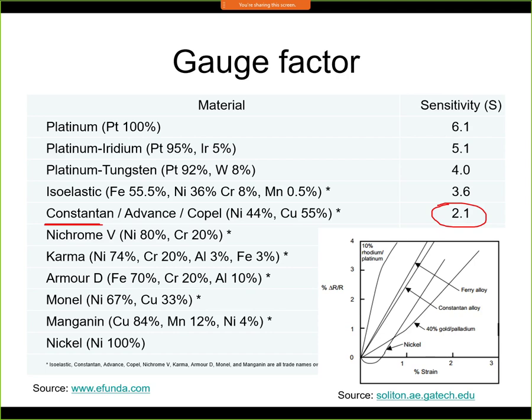The typical value of strain that we measure with strain gauges is somewhere in this region. So let's say up to 0.5% of strain, maybe 1% strain. We simply want to avoid plastic deformation in the material, so we have a limited strain that's available. Here you can see the Constantan alloy, which has nice linearity here. It works quite well in this region. We can see another Ferry alloy. It's not here in the table, but it has similar properties to this Constantan alloy. We can see also some other alloys like gold and palladium, but obviously this would be very expensive. The same here, rhodium and platinum. So rare metals are not used for strain gauges for the reason of price and also the reaction to temperature eventually.